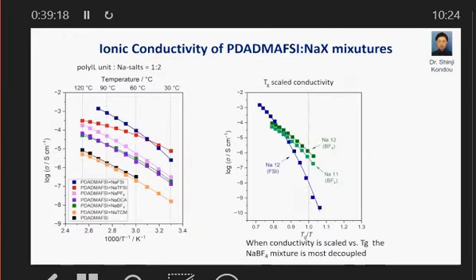We measure the conductivity of these systems, even though they were heterogeneous. We see on the left-hand side that the FSI and TFSI, the black and the brown, are the most conductive here, the FSI being the most conductive. The other ones aren't that bad. I mean, considering that they're so heterogeneous, we are measuring some conductivities, except for the TCM system here, which doesn't dissolve at all. So this was, again, a bit disappointing, but nevertheless, we are seeing some conductivity.